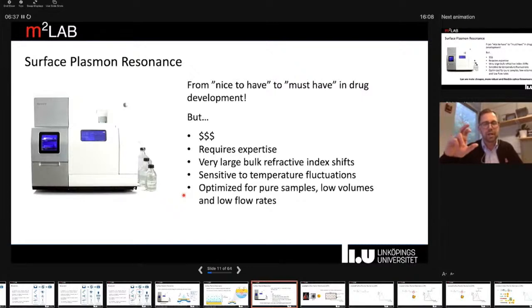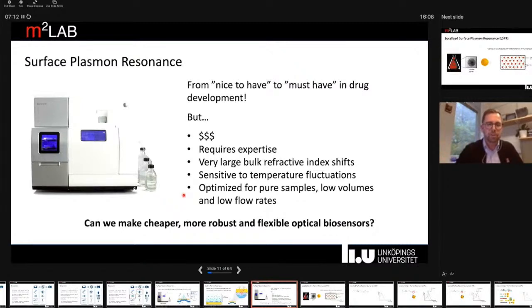refractive index changes occurring a bit further away from the surface than we are necessarily interested in, giving rise to a large bulk refractive index shift. And this, in combination with some other aspects, makes these instruments very sensitive to temperature fluctuations. And they are essentially optimized for pure samples, low volumes, and relatively low flow rates. But excellent for research purposes, especially in drug development. What my research is about is essentially to see if we can make cheaper, more robust, and flexible optical biosensors with similar performance as you can essentially obtain from surface plasmon resonance based transducers.